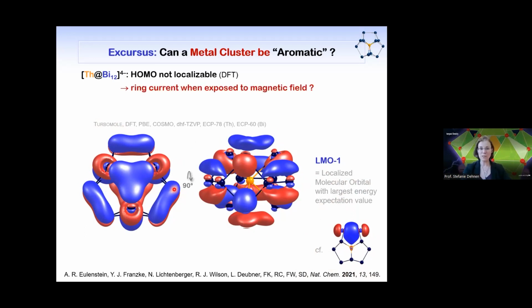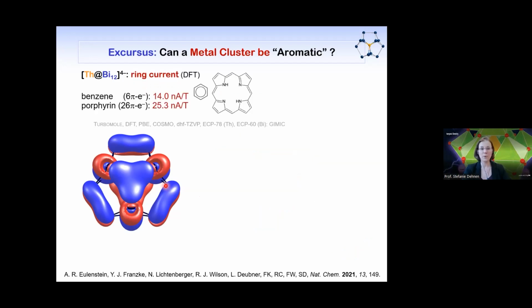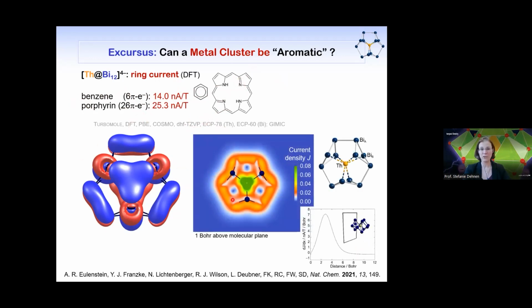Okay, we calculated that. We exposed this molecule in theory to a magnetic field. And what comes out of these kind of calculations is a number. And here you are the numbers that we calculate for benzene or for porphyrin. Just take these numbers as they are. So this is nano ampere per Tesla. We have a number of 14 or 25 here for these well-known aromatic molecules. In our case, we first found that we have a ring current. You see this again, 1 Bohr above the molecular plane. It is an integration box for it. And second, we can calculate a nice number. And this number is very similar to what we find for porphyrin.